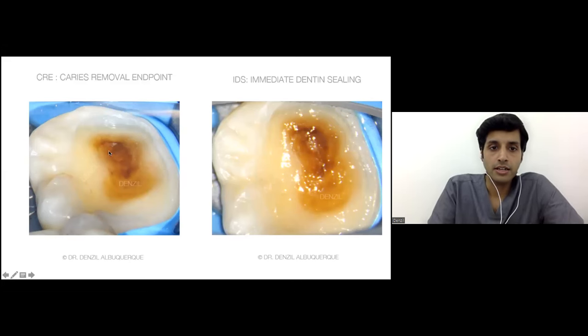Following the caries detecting dye, we go deeper, but up to a point that is about 3 millimeters and not more than 5 millimeters occlusally. Then go for the immediate dentin sealing. You can see the bond applied on the dentine itself. You can see enamel over here. It is not at all in the zone.